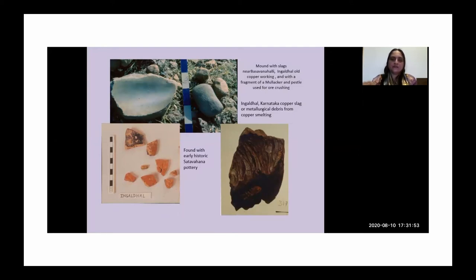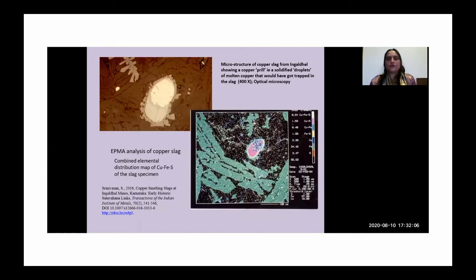And typically with the slag which has been tapped from the bottom of the furnace, you see a certain flow texture, which is why it is generally referred to as tap slag. And so, well, when we use the tools of microscopic examination and so on to study the slags as well as artifacts, that gives us a lot of useful information which can help us to reconstruct the processes to some extent.